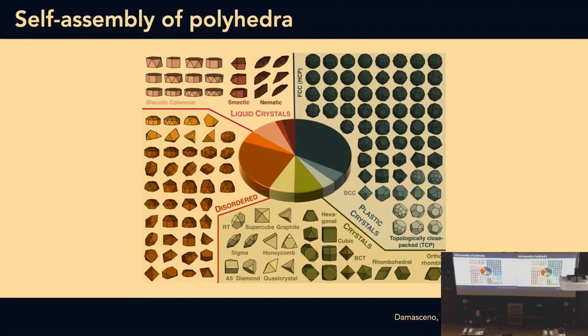If you take lots of copies of tetrahedra and bring them as closely together as possible, you'll form a dense packing, but it won't fill space. And that dense packing is unusual in that it's characterized by quasi-periodicity. It's a quasi-crystalline arrangement that you get with tetrahedra. So it's a simple question to ask, but it has some pretty subtle answers.